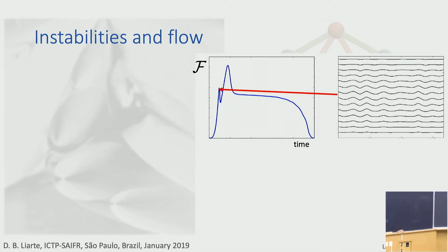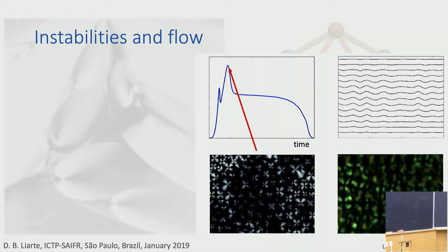And then if you continue to increase the gap, at some point there will be another instability and there will be an array of focal conic domains. And that will decrease the energy again. At least in this protocol that I'm considering, I'm going up, up, up until some point and then going back down to where I was at the beginning. This is the free energy profile. This is the texture when you have this array of focal conic domains. And it agrees pretty well with experiments performed by Itai Cohen's group at Cornell.